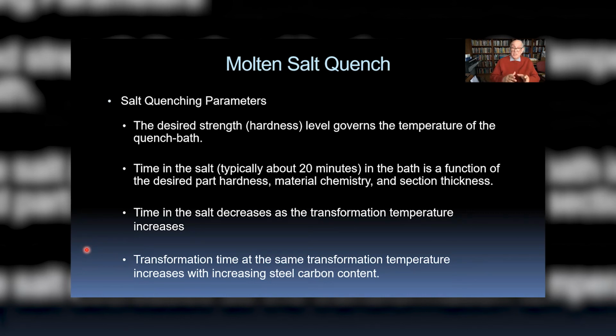So a typical time in the salt is somewhere in the range of 18 to 20 minutes. I've seen parts held in salt for as short as 10 or 12 minutes and for as long as 30 minutes. But it depends on the thickness of the part, the material, and ultimately the desired hardness we are going to reach.